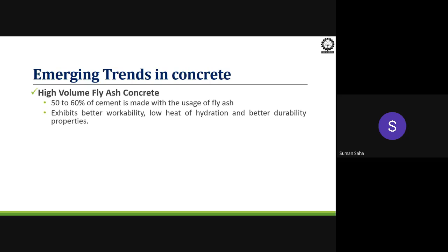Nowadays, people are avoiding using OPC. But in that PPC, Indian standard guidelines say we cannot use more than 35% fly ash. When we are crossing 50 to 60% replacement, we can say the volume of fly ash is quite high, but again subject to achieving all the desired properties. If we use 80% fly ash and we are aiming for 30 MPa concrete, but at the end of 28 days we are gaining only 10 MPa, it's no use. So by doing experimental research, we can finalize how much percentage of fly ash we can use.